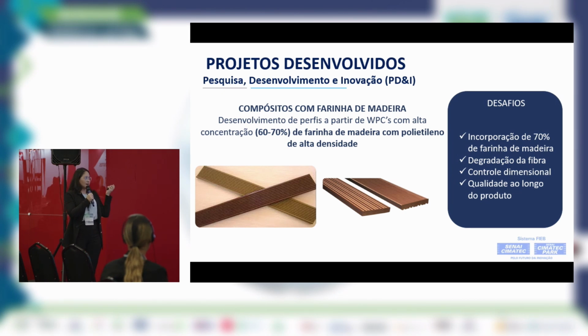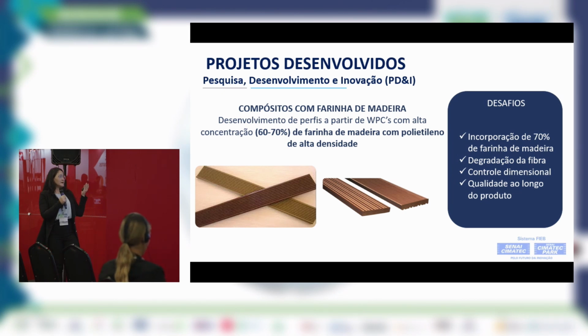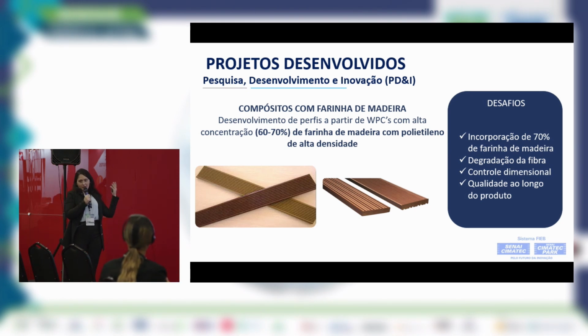We have another one for the deck board production using ground wood with very high concentrations of fiber, 60 to 70%. If you work with composite development, it's difficult to incorporate such a high content of fillers in the polymeric matrix. This is a challenge in itself. So this material was used to produce the profiles.